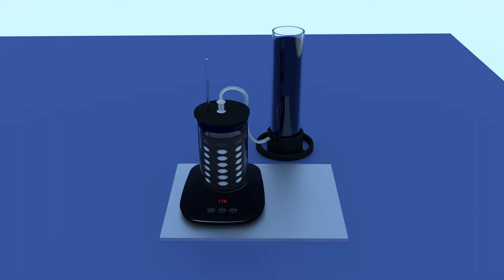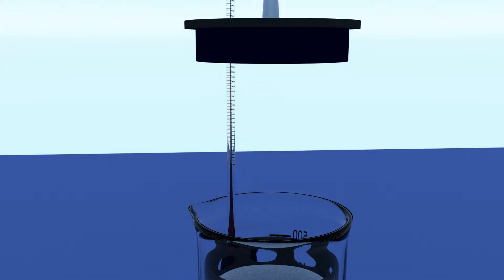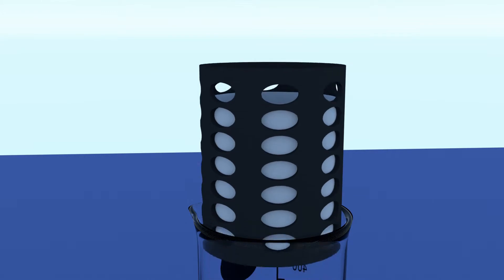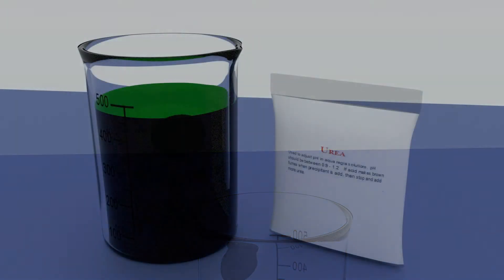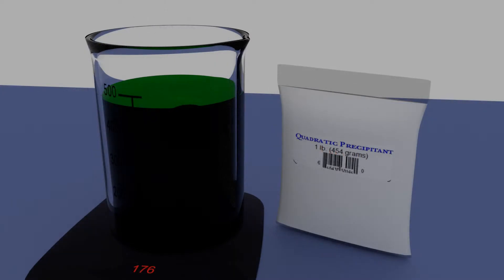Metal is dissolved into solution. Stones and other materials that didn't dissolve are separated from the solution by removing the basket and filter pouch. Free cyanide ions that are in solution are neutralized by the addition of urea. A selective precipitant is added to the solution to turn the dissolved gold, and nothing else, back into solid in the form of particles.